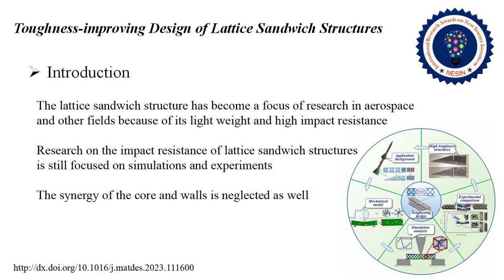For characterizing their impact properties, scholars have explored the effects of geometric factors on sandwich structures, such as the thicknesses of skins, configurations, and sizes of cores. Studies have shown that the core is the key to improving the impact toughness of sandwich structures. Some researchers noted that, in metal sandwich structures, the impact energy is mainly absorbed by both the core and the top plate, while plastic dissipation is the main form of energy absorption for this structure. Some researchers found that a core with low density shows a better cushioning effect, and when the density increases to a certain degree, the cushioning effect decreases.